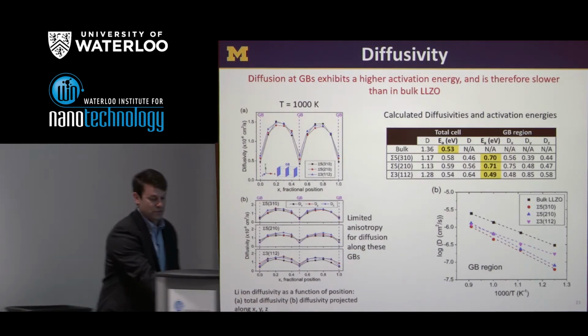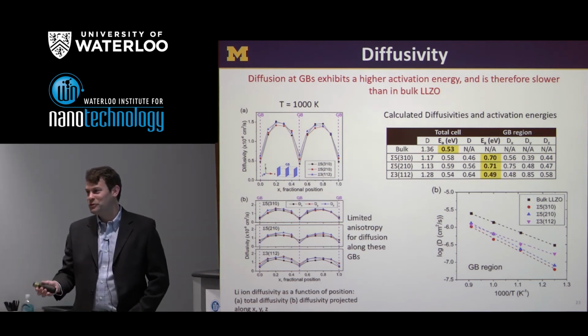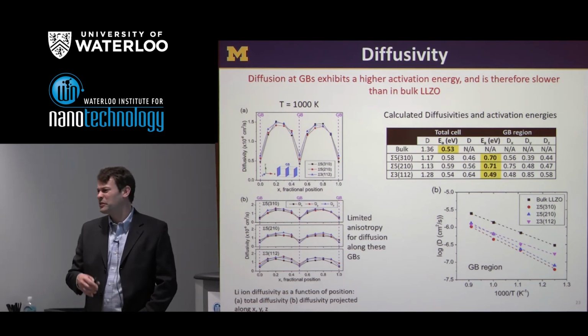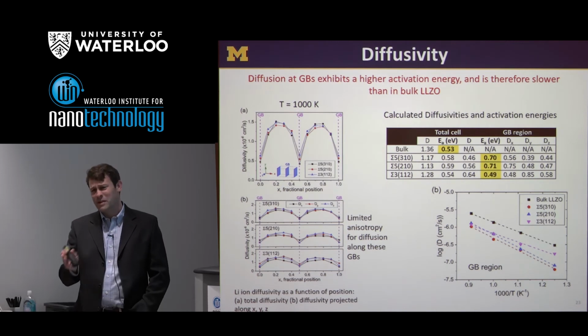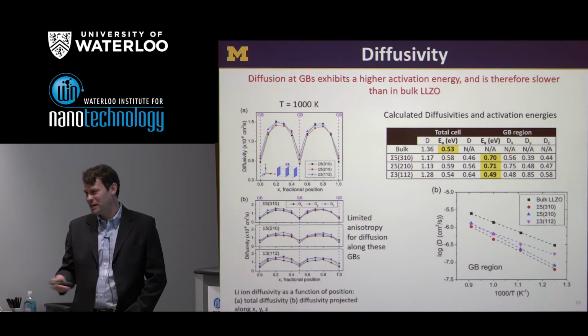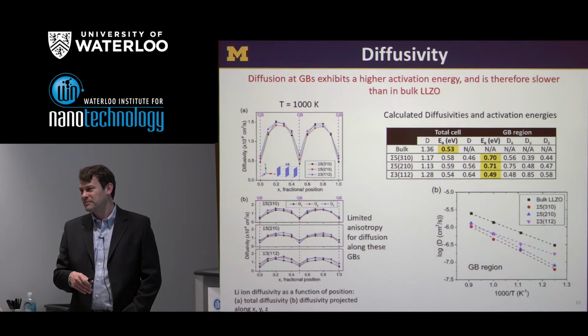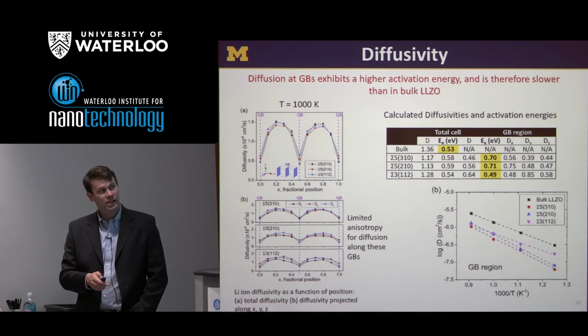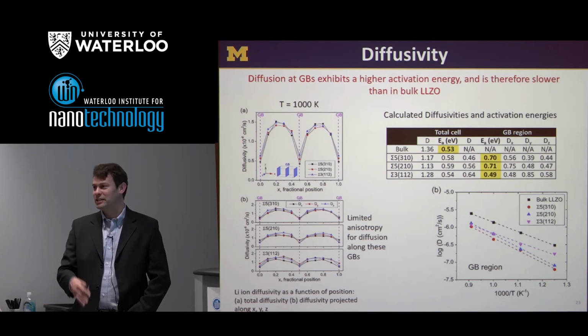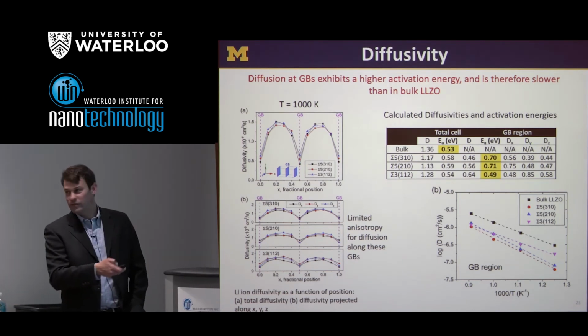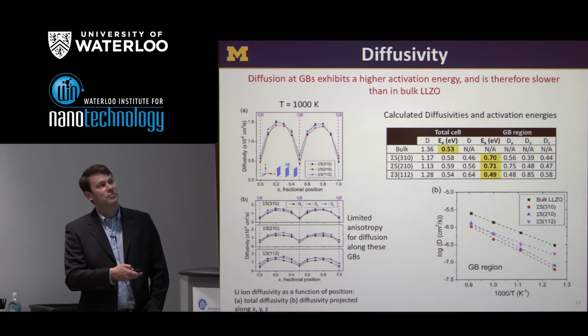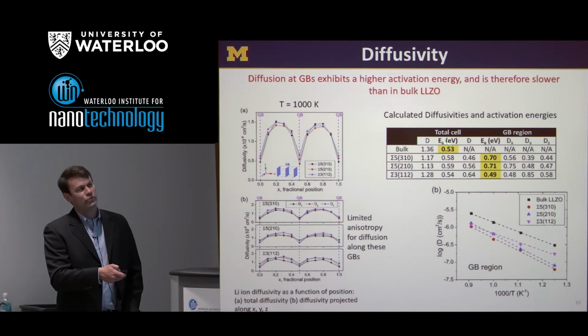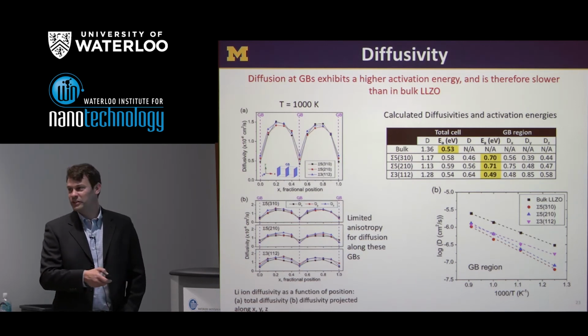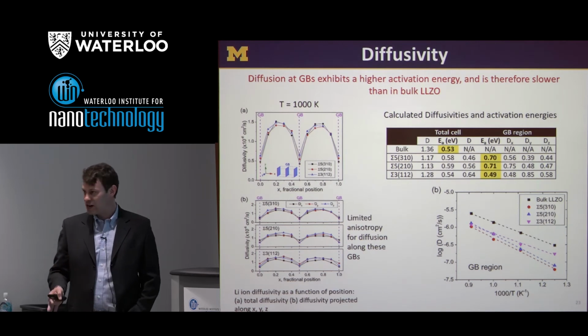Well, the experimental value depends upon who's measuring it, but I'd say around 0.3, 0.35. There's values actually all the way from about 0.2 to the midpoint. Yeah, I saw numbers around 0.25. So this particular interatomic potential tends to underestimate the ionic conductivity of lithium. So that's why you see this value, which looks high to you. So here I'd say it's most justified to compare bulk relative to grain boundary and not read into, say, the absolute conductivity.